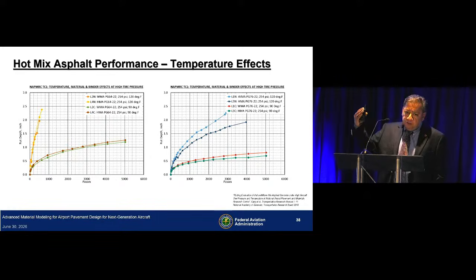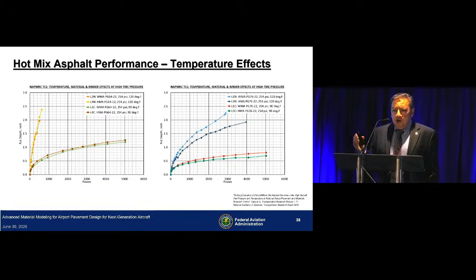So we'll start from the top layer of the pavement, the asphalt layer. If you remember, in design, asphalt modulus is fixed with no consideration given to the binder grade or the temperature effects. So this was some research done at the National Airport Pavement and Materials Research Center, where we have the ability to control pavement temperature and test these sections under controlled temperatures.